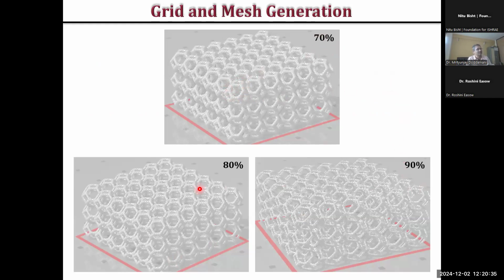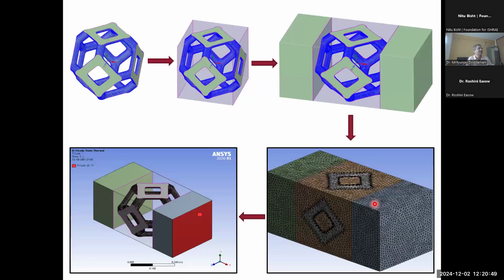We varied the porosity level also, because this porosity level plays a very vital role for the heat to take a specific path on the struts and so on. So we varied from 70, 80, 90. We did the simulation. We applied the boundary conditions using a steady state thermal condition, hot plate and cold plate. And then we maintained 100 degrees C at one end and 25 degrees C at the other end, because we wanted to know the heat flux through this structure, which is a Kelvin structure.